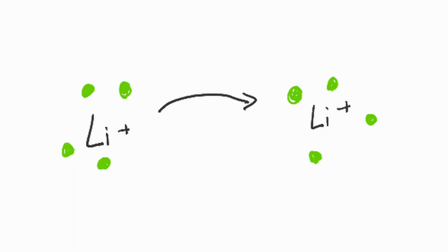But one thing I want to point out here: highly conductive electrolytes don't necessarily have weak coordination. They're just able to exchange coordination very quickly. For example, in a liquid, lithium might be surrounded by a bunch of atoms, and then it gets passed on to a new bunch, and it moves through the chain that way. So in liquids, we have dynamic coordination, or very easy rearrangement. In polymers, the coordination rearranges only when the chains move. And in inorganics, we have no coordination rearrangement because the lattice is fixed.